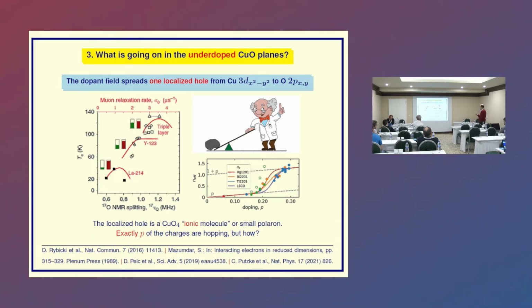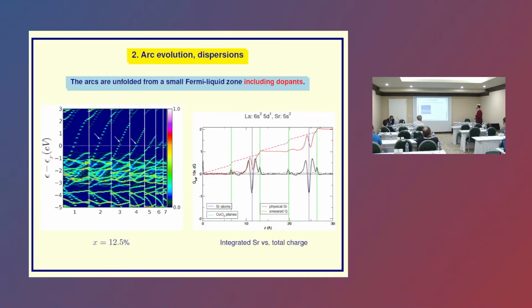This is the figure which you already saw in Neven's talk, and you can see that there is a broad transition from p to 1 plus p. This is theoretically a very important point, because these broad transitions happen in the average quantities when you have a first order phase transition microscopically. Because a first order phase transition has this microscopic characteristic that at a given site it always is either 0 or 1. It is always discontinuous at a site, but because not all sites flip at the same time, you have a sort of smoothed out transition macroscopically. This is very different from a second order phase transition, which would have a discontinuity in the occupation number visible on the average.